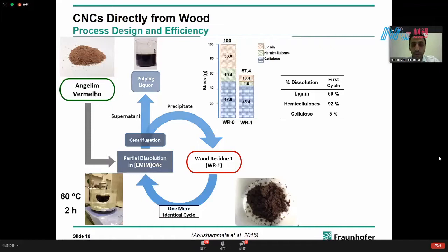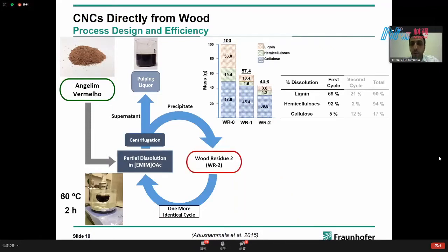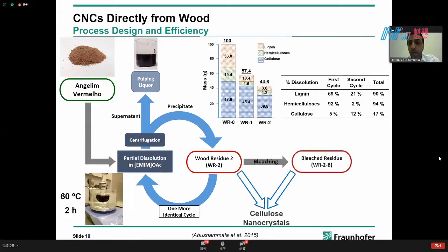We repeated the process a second time to remove the residual lignin. So we were able, at the end of the day, to remove more than 90% of both lignin and hemicelluloses, while a small amount of cellulose was degraded, hopefully this part being amorphous cellulose. We bleached the residue, and from both pulps, bleached and unbleached, we were able to extract nanocrystals.